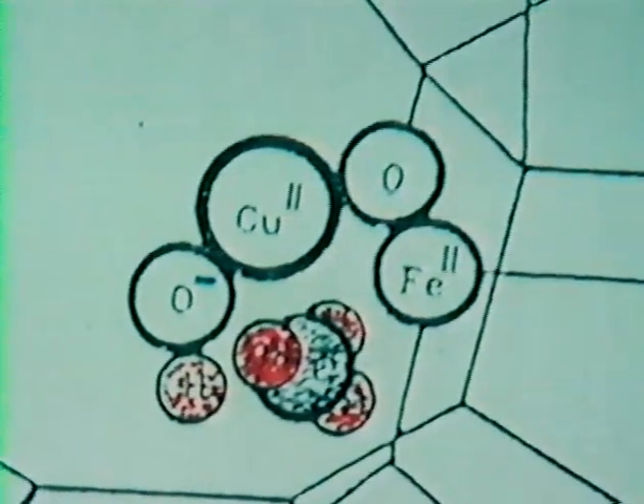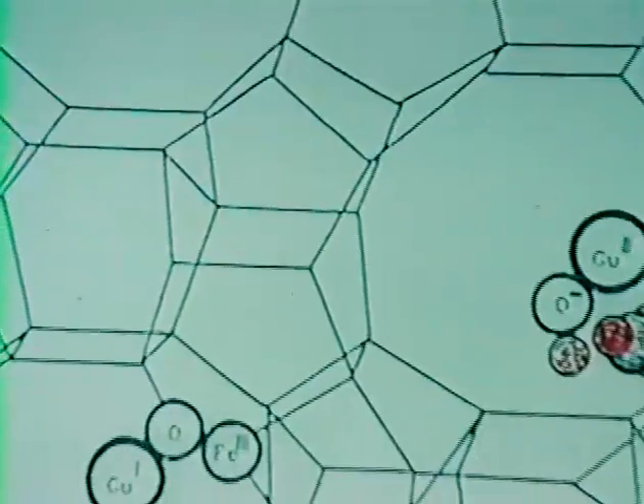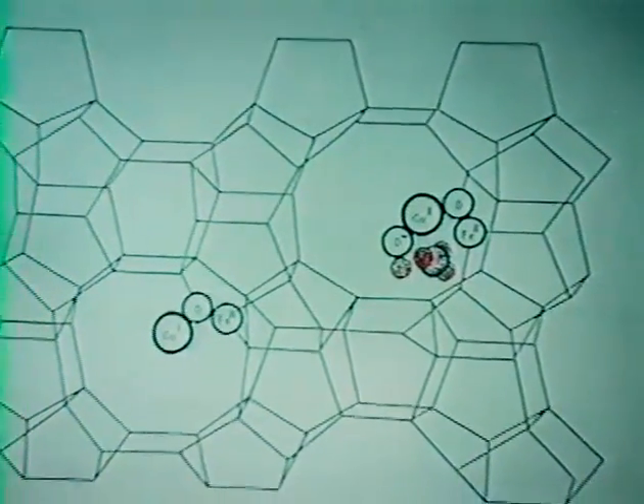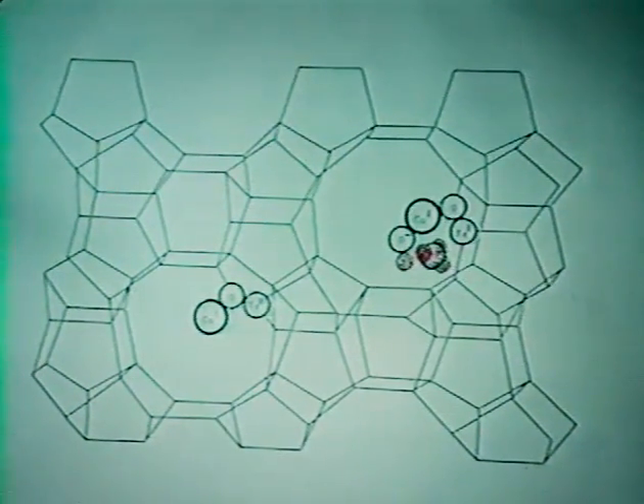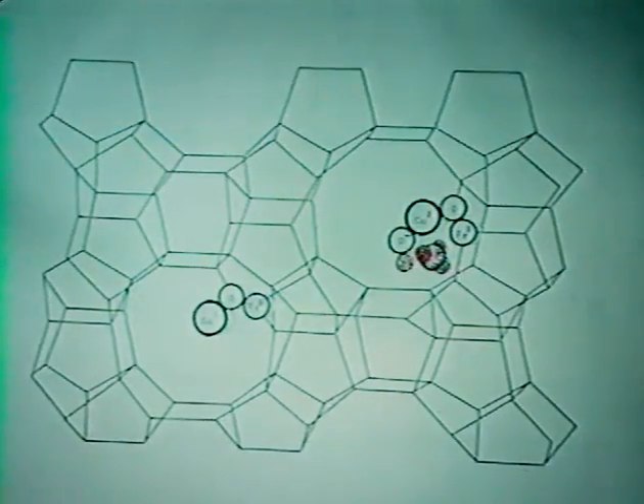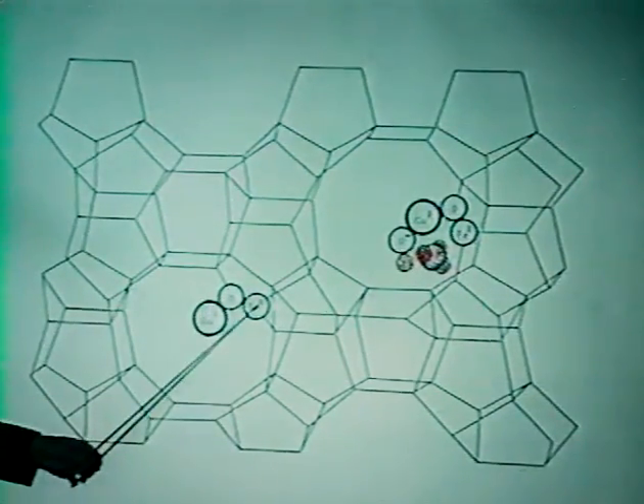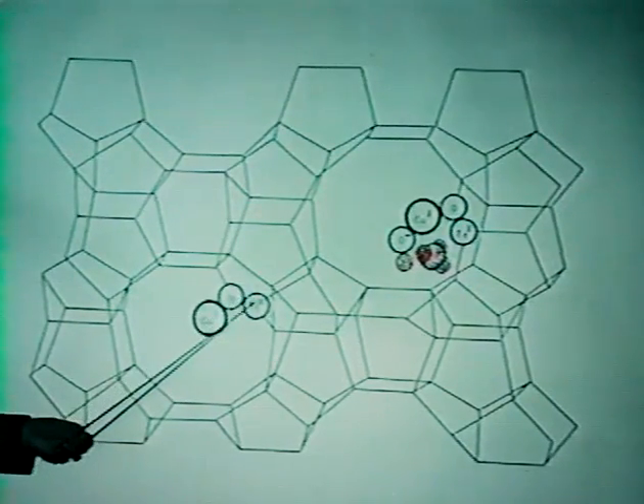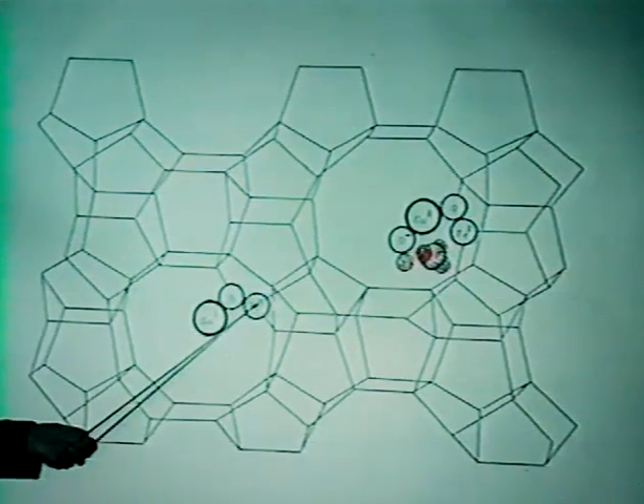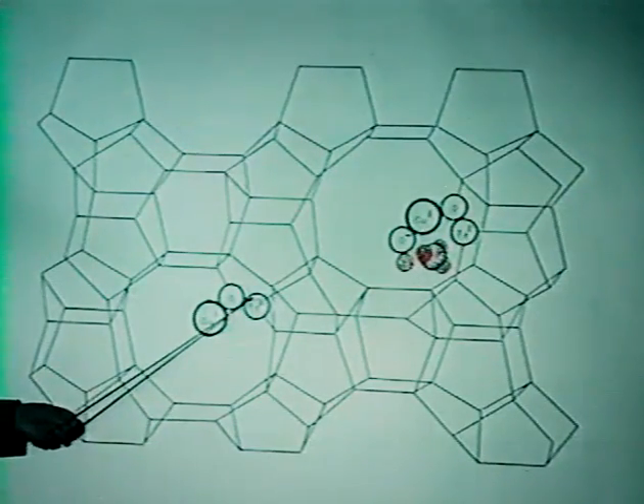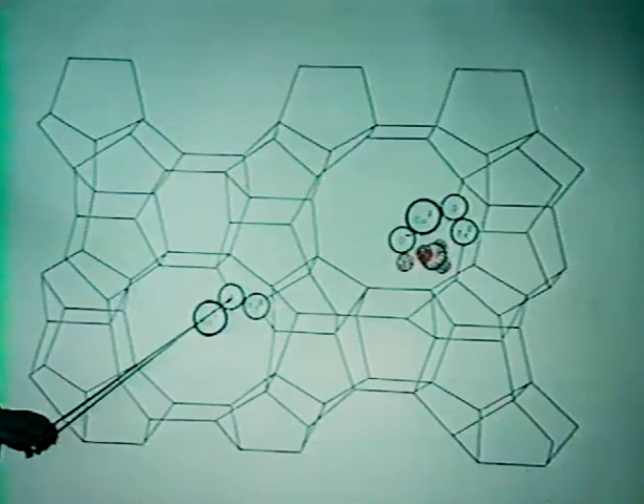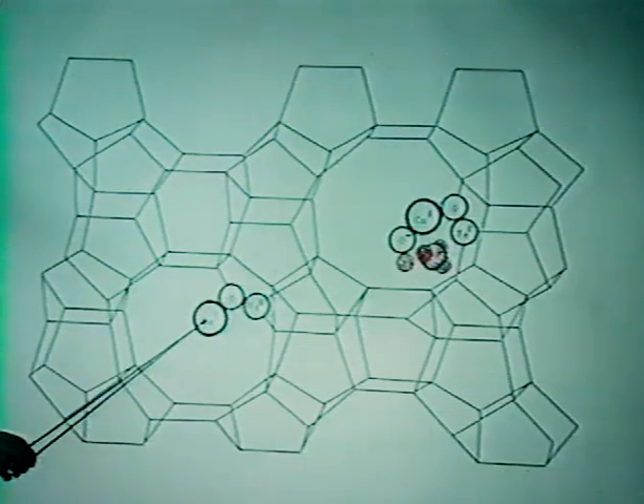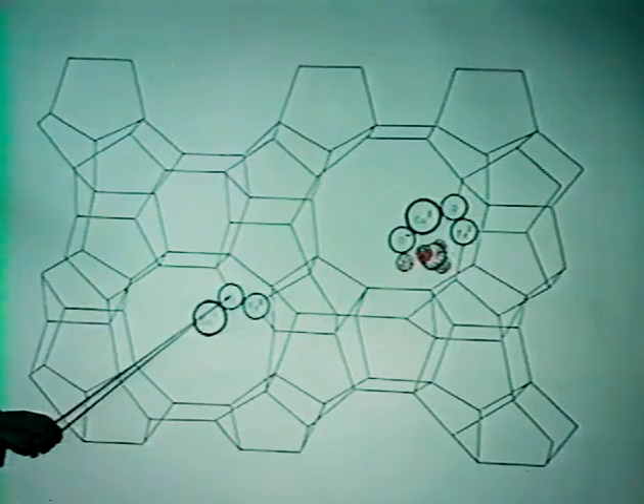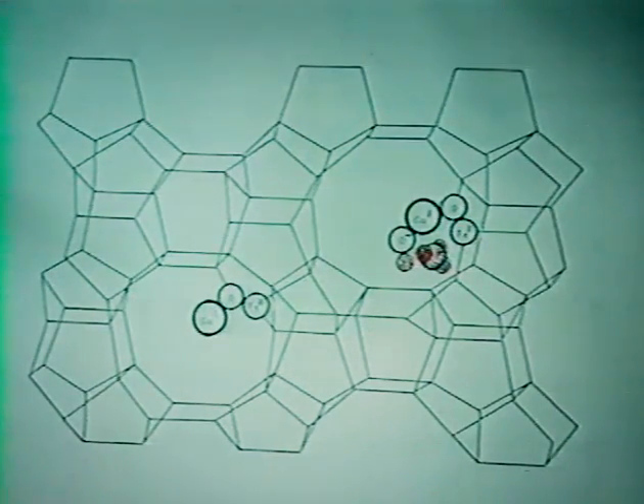And actually, if you take a look at these methanotropic bugs, the bacteria, they have iron and copper in them also. Now, this chemistry is not a chemistry that occurs at room temperature. This is a chemistry that occurs at high temperatures. But the idea was the following. Take a framework in the ZSM5, exchanged or synthesized with iron 3 instead of aluminum 3, you can put it in there. And this is the framework oxygen, put the copper in the ion exchange site, and you have a kind of a Coulombic pair which is separated by an oxygen bridge.